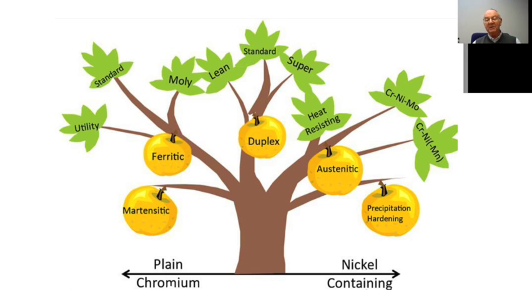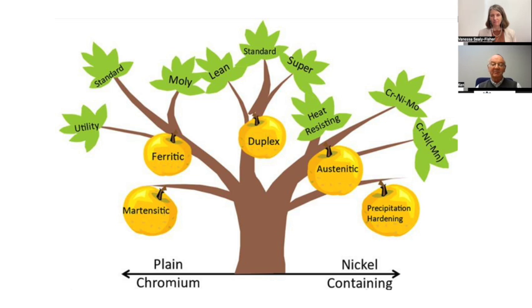So alloy developers said, well, how can we get the benefit of both worlds? And they could do that by bringing from obscurity the so-called duplex stainless steels, which have a combined structure of ferrite and austenite. And I say bring it from obscurity because duplex stainless steels were actually developed a long time ago as well. But the steel making technology didn't allow for the other properties we want from materials, most notably your forming, welding behavior, etc., to be of a suitable standard for them to become widely accepted materials of construction. So in their early form, they were primarily just used as casting materials. But it's only in perhaps the last 30 to 40 years that they've emerged as very useful materials of construction.